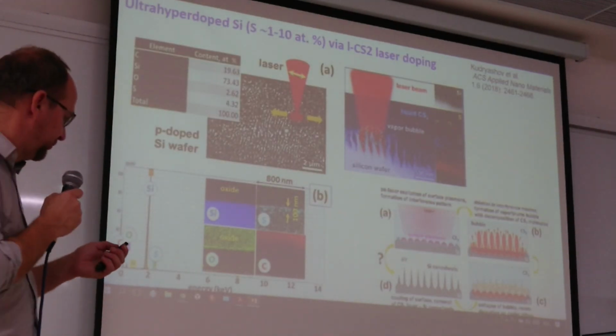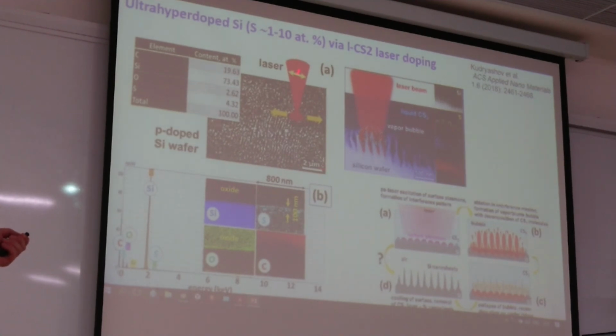And in our work, we have used lasers to scan the silicon surface in liquid carbon disulfide. Carbon disulfide, CS2, is a composition of carbon and sulfur, and it can be easily dissociated into carbon and sulfur. And when we scan the silicon surface, we have 2 effects. We are producing surface nanostructures, and we introduce sulfur inside. Chemical analysis by energy dispersive spectroscopy indicates we have sulfur at about 4 atomic percent in the surface layer.